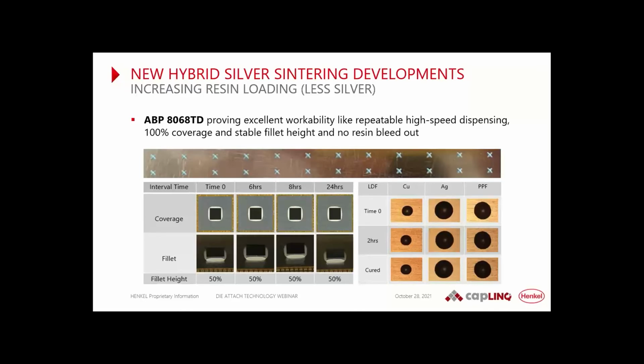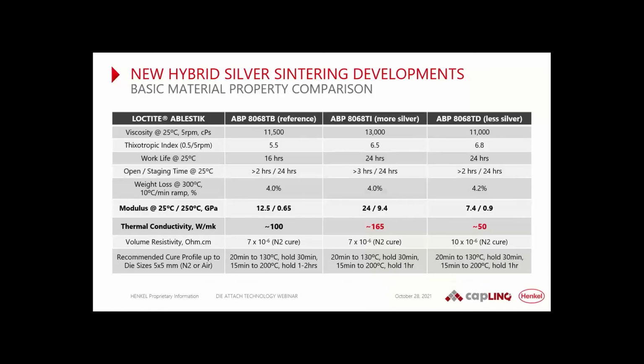And also again, really designed by a die attach specialist, and easy to process. You see beautiful fillets, and this is what actually you don't see the difference between a sintering paste and a standard die attach paste. So here you can see the comparison. Let's say the TB high volume runner, higher silver content and lower silver content versions, with the main difference basically modulus, stress level, and also thermal conductivity. So please feel free to reach out to us if you would like to know more or try it out.